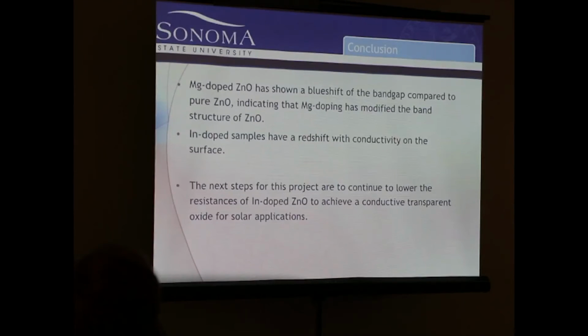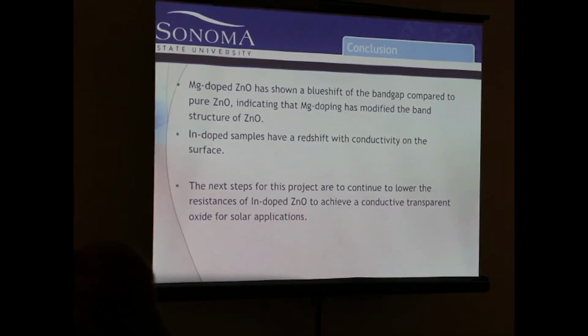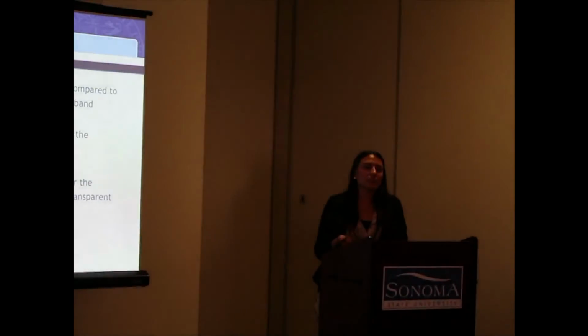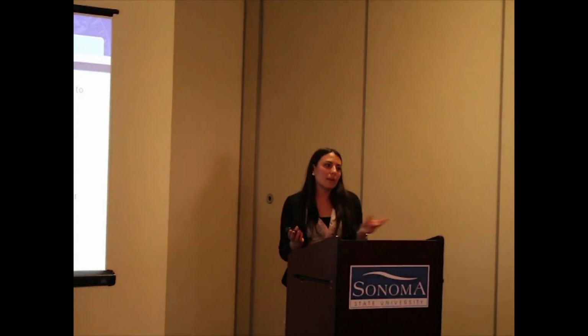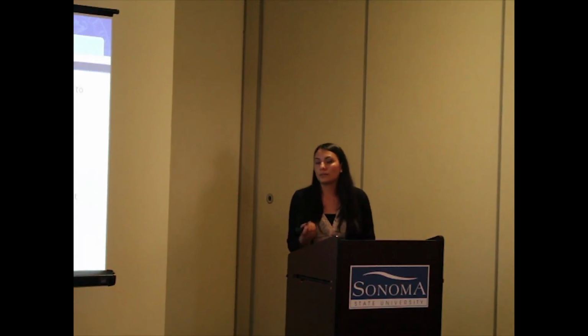And so the next steps for this project are to really just continue to lower the resistance on the surface. So that can mean that we have to increase the percentage of indium, so we can go to like 5 or 6% and see how many layers we have to do, or we can just continue like maybe doing 30 coats of the thin film onto the surface. And so that will really just help us achieve this conductive transparent oxide for solar cells, because then we can even double dope the sample, so putting magnesium and indium all in one and seeing how the band gap is tuned with those circumstances.